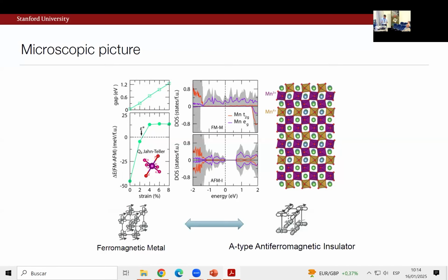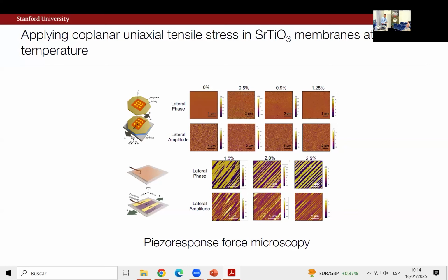So this is kind of exciting for us that this is an example of using strain to tune, hopefully, some of these competitions on fairly large energy scales. A second example, going back to strontium titanate, is to see what happens when we apply uniaxial, in this case, I'll show you tensile strain for these sorts of membranes at room temperature.